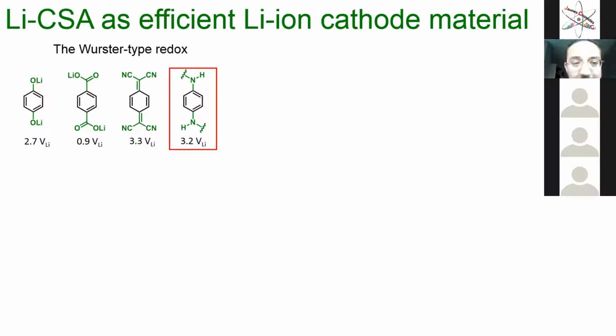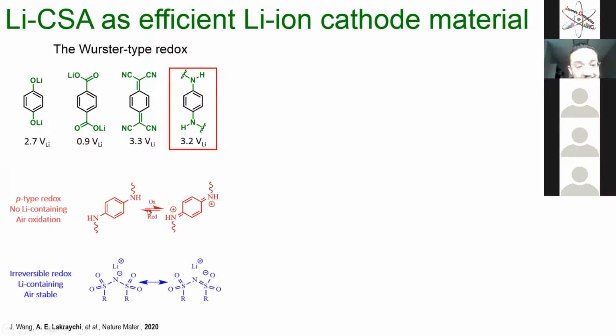Remember, prior to any molecular design, we are looking for something that intrinsically should have a higher potential, above 3 volt, and be lithium containing. If we look at this conjugated amine, it has a potential of 3.2, but it's not lithium containing. But as you can see, there is a proton here that can be substituted with lithium. And this will help us design a new class of organic materials that is lithium containing, high voltage, and with reversible redox reaction. This one, if you use it as such, will not store cations, it will store anions because it belongs to the p-type redox mechanism. It's not lithium containing and it gets oxidized in air.